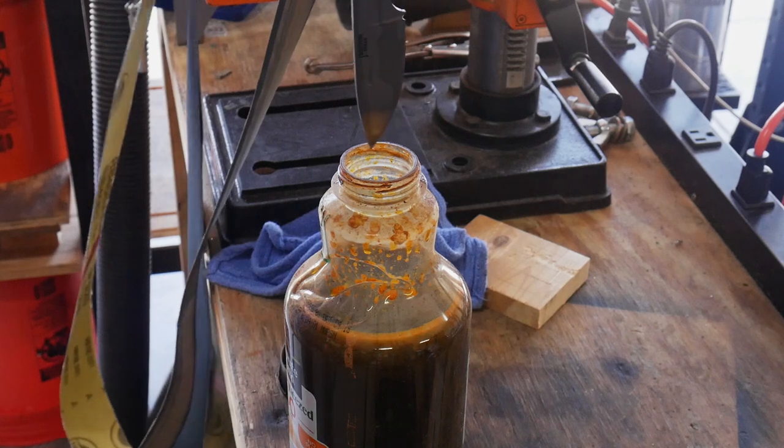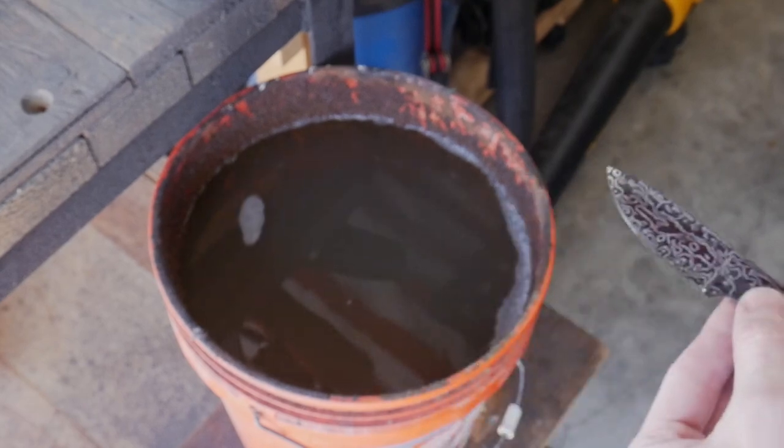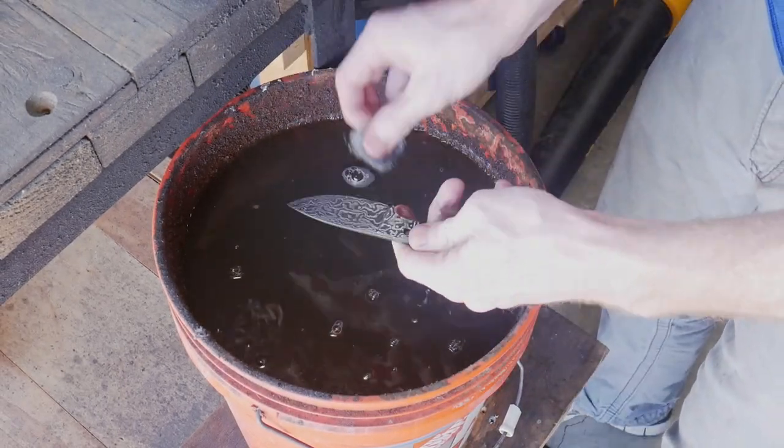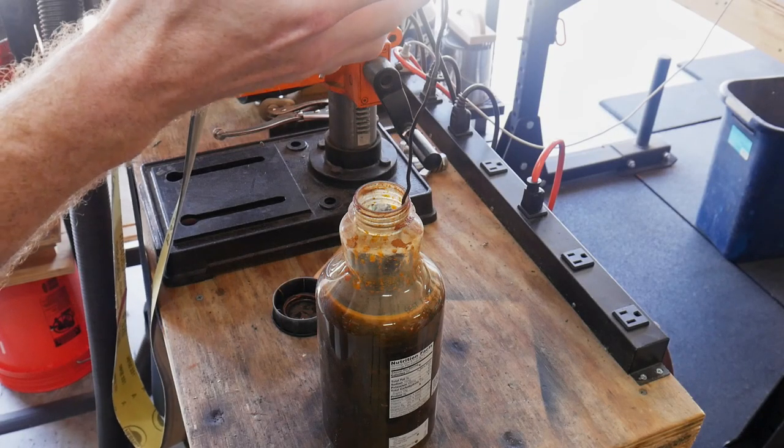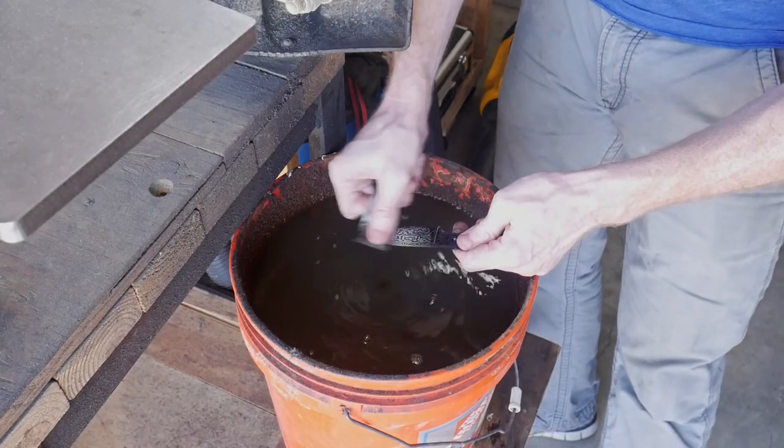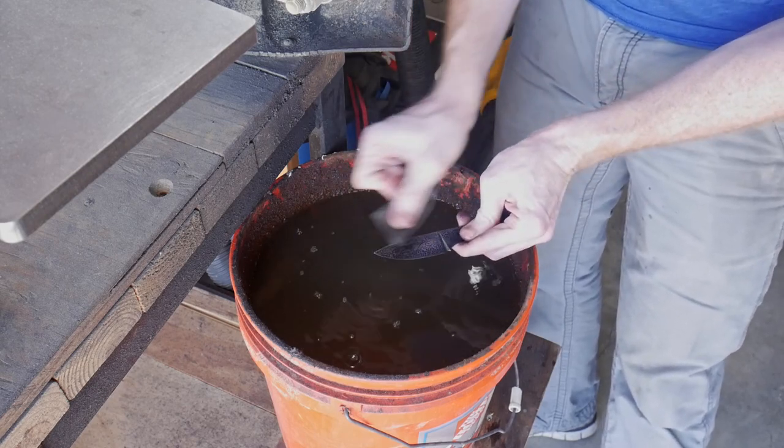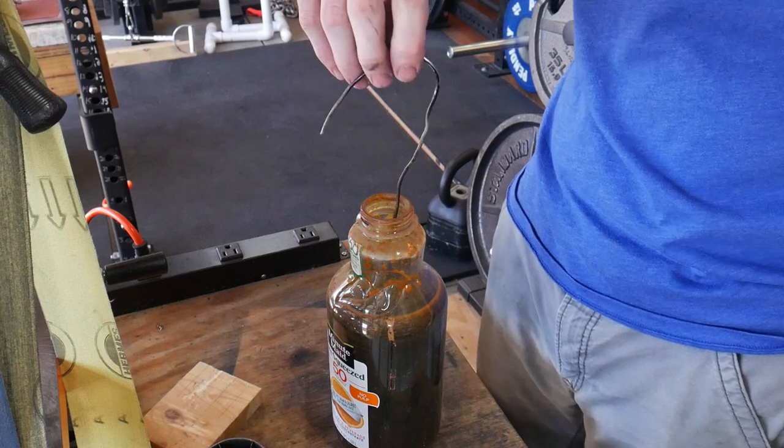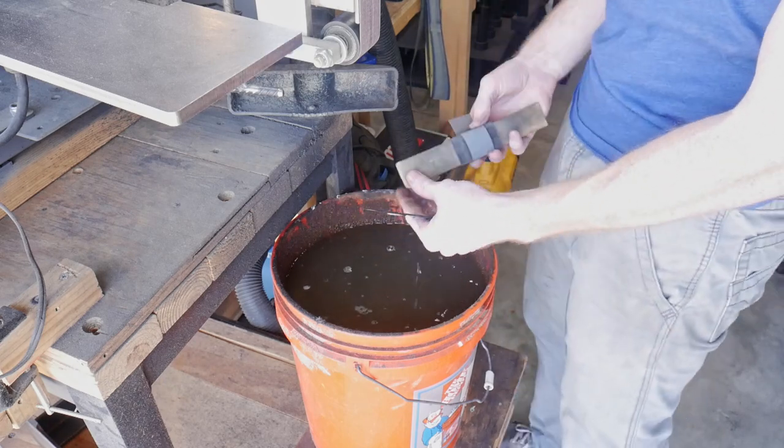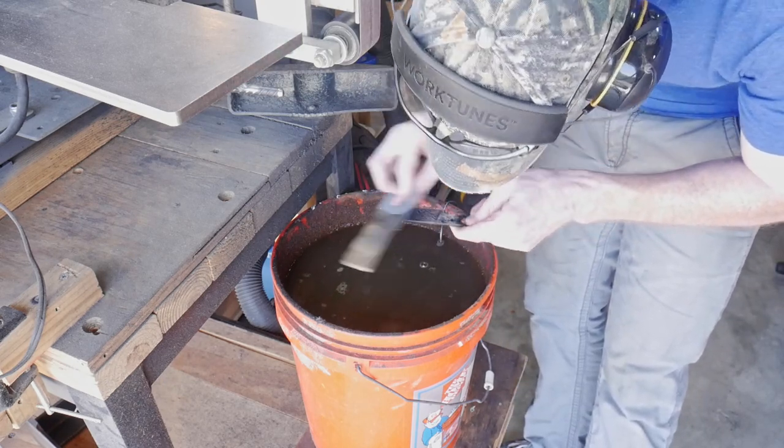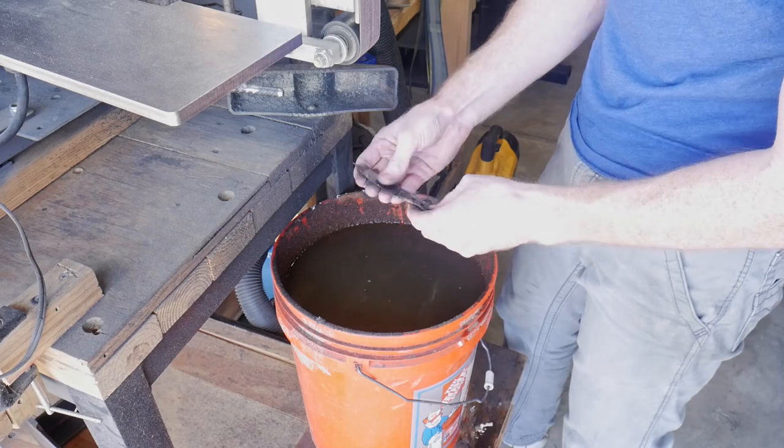My first etching cycle I etched for six minutes in a 50-50 ratio ferric chloride water mix. You can see it came out nice and dark here and then used some steel wool to knock off all of the buildup. Then put it back into the etchant for two minutes and repeated this cycle three times. The final two times I was using a piece of 2500 grit sandpaper just to make all of the 15N20 nice and shiny. I then used some window cleaner with ammonia in it to neutralize the acid, and just for good measure, I coated it down in baking soda as well.